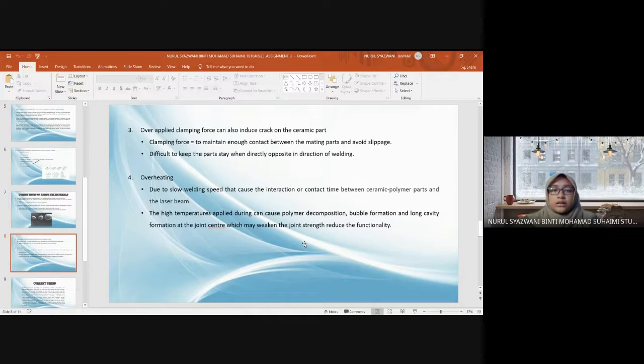And the third one is that over-applied clamping force can also induce cracks on the ceramic part. The clamping force basically is used to clamp together the polymer and ceramic substrate in order to maintain enough contact between both parts and also to avoid slippage. However, since ceramic is a brittle material, it is hard to make sure that the clamping force applied is sufficient enough and does not deform the ceramic part.